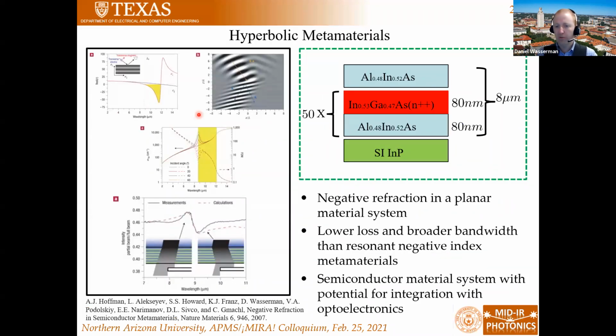There's one more thing that I want to mention, which is that with this ability to control permittivity, we can now start thinking about incorporating regions of semiconductors that have negative permittivity with regions of semiconductors that might have positive permittivity. And this led to work done by my colleague Anthony Hoffman when he was a PhD student at Princeton, where he demonstrated that you could make what's called a hyperbolic metamaterial using alternating layers of highly doped and undoped semiconductor materials. And so this allowed for effects such as negative refraction and this highly anisotropic response in a layered metamaterial structure.